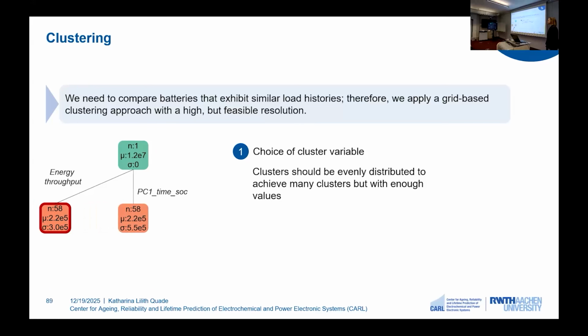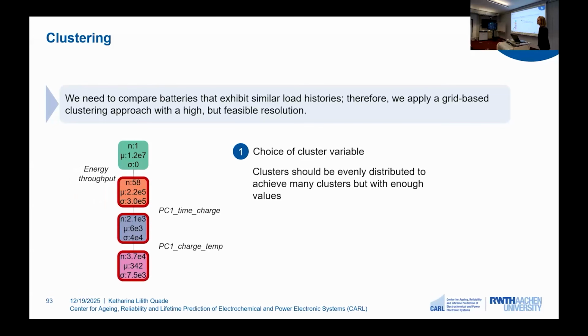We continue to compare this with other reasonable variables from our data set, and we always see that our sigma is greater compared to our energy throughput sigma. And therefore, for the first iteration, we stick with energy throughput. And then we repeat the whole procedure for all other variables, and we stop when we do not have a significant change in our cluster sizes and cluster spreads. And this yields 3 cluster variables: energy throughput, PC1 time charge, and PC1 charge temp.